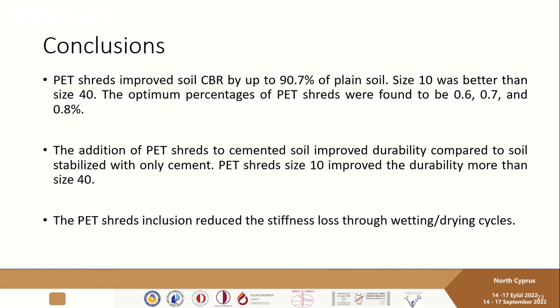Yeah. So if we come to the conclusion, we can see that the PET shreds addition to the soil improved the CBR up to about 90% of plain soil, and size number 10 was better in improving the CBR of the soil than size number 40. And also the optimum percentages of the used ones were found to be 0.6, 0.7, and 0.8. Also, the addition of the PET shreds to cemented soil improved the durability compared to soil stabilized with only cement, and also size number 10 was better than size number 40. Also, the PET shreds inclusion reduced the stiffness loss through wetting drying cycles.